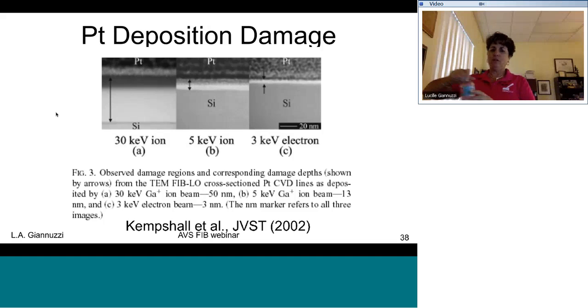So if you take a look, the image on the left is for 30 kV gallium on silicon, and you see about 50 nanometers of damage here, which is consistent with 50 nanometers of 30 kV gallium on a silicon surface. If you go to 5 kV gallium, that damage is reduced. Now, if we use electron beam deposition on top of silicon and cross-section that, this bright area here is consistent with just native oxide on silicon. And so if you're really worried or want to analyze the very top surface of your sample, you can do one of two things.